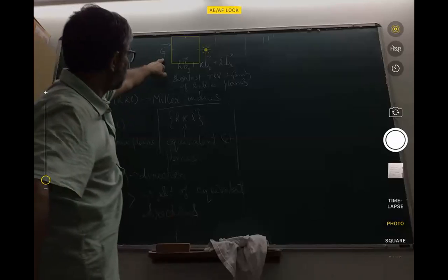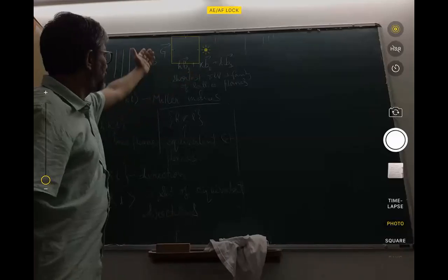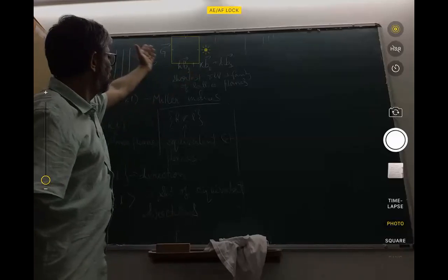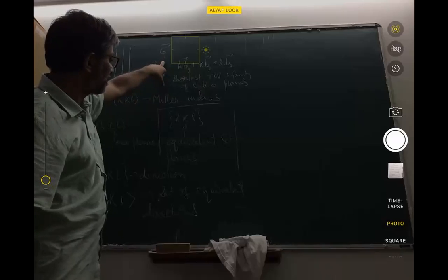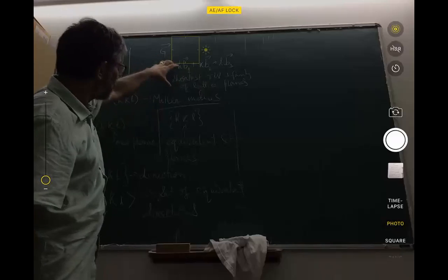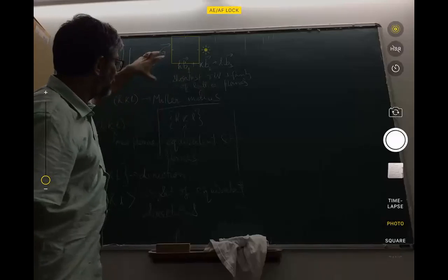And because these h, k, l are integers, because we know that integer combinations of the reciprocal primitive cell vectors generate all the reciprocal lattice vectors for this lattice. Therefore, since we are saying that this is the shortest reciprocal lattice vector perpendicular to this set of planes, there are no common factors between h, k, l. Okay, so that is something you should keep in mind.